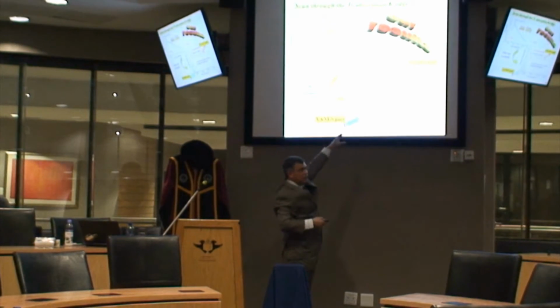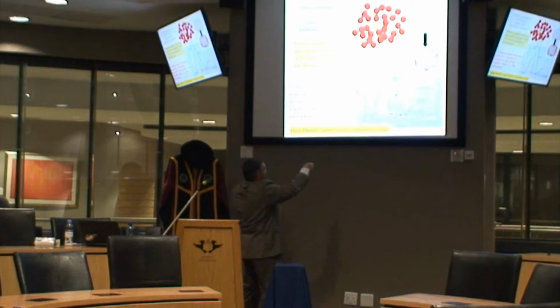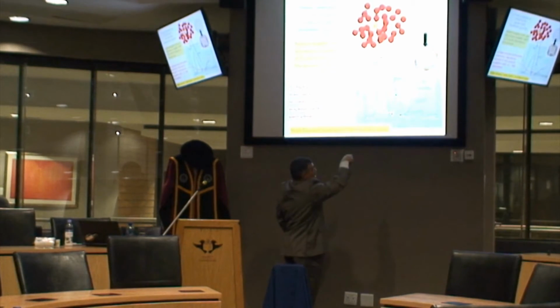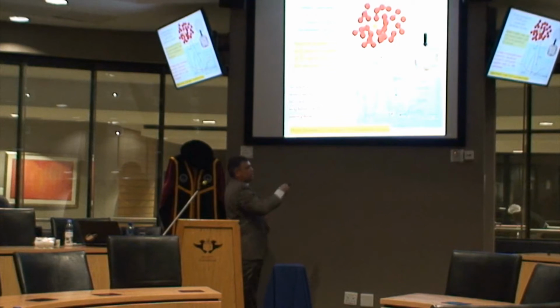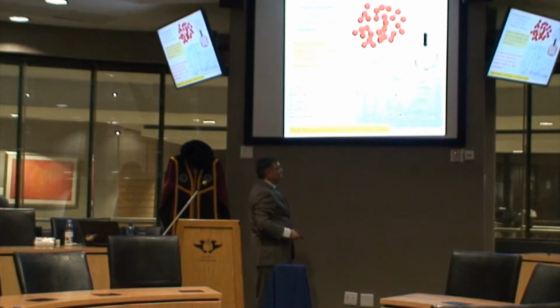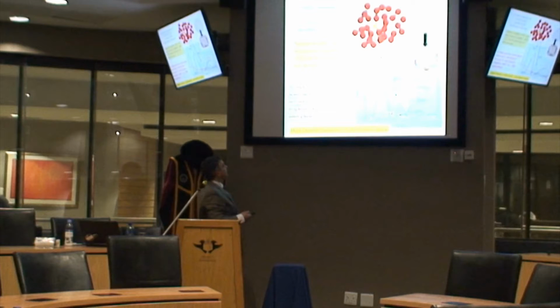And I do a mathematical manipulation of this for my physics colleagues. I take a Fourier transform. Okay? And I have, call it intensity on this axis versus distance from the central titanium atom. And it tells me about the coordination shells around the titanium. Very clearly, a titanium oxygen coordination shell. Very clearly, a titanium next nearest neighbor coordination shell at low pressures. And then these peaks disappear. It means that at high pressure, this grain has become fully disordered. More information than what the simulations give us. It's almost as if you have a liquid phase in solidified form, if you can imagine that. We call it a high-density amorphous phase.